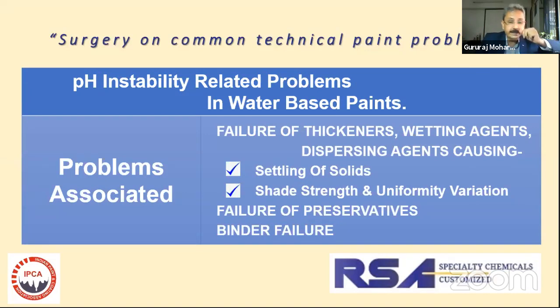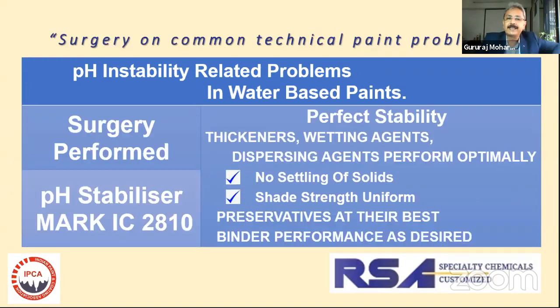So these are pretty serious problems which can be very easily taken care of by a simple addition of a pH stabilizer. What a pH stabilizer does is it takes care of the pH change. It remains inactive till required, and as the pH starts changing, it will start neutralizing and taking care of the pH. And if the pH is stable, your thickener, your wetting agent, dispersing agent, preservatives, binders, they all perform perfectly.